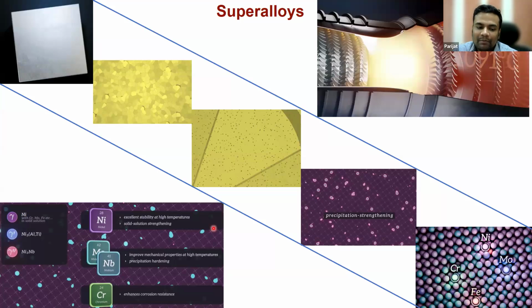And chromium also we add. We added chromium, 8 to 10% chromium. It will give a corrosion resistant coating, because if you add chromium, it will quickly form chromium oxide on the surface. It's a self-healing oxide layer, and that oxide basically protects the material inside, like nickel or molybdenum and other things. So the nickel-based superalloy is strengthened by precipitation strengthening. The precipitates can be of two types. One we call gamma prime, another is gamma double prime. The gamma prime is Ni3AlTi, and the gamma double prime is Ni3Nb. So these are the two types of precipitates which give rise to this kind of strength.